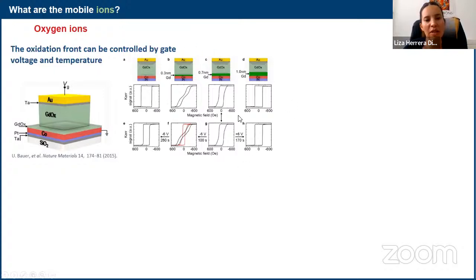Here what they did was grow different layers, because if we assume that with a voltage we can oxidize or reduce what we have in our stack, then they could grow different layers, saying, well, let's make an interface with pure gadolinium that is thicker and thicker next to the cobalt.